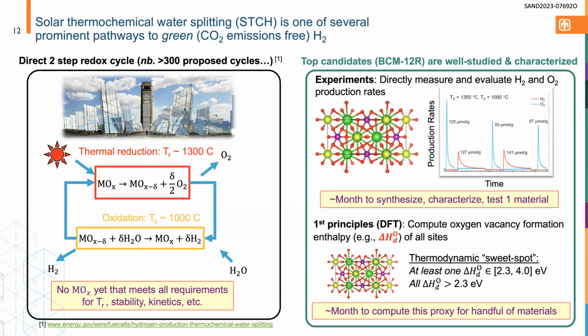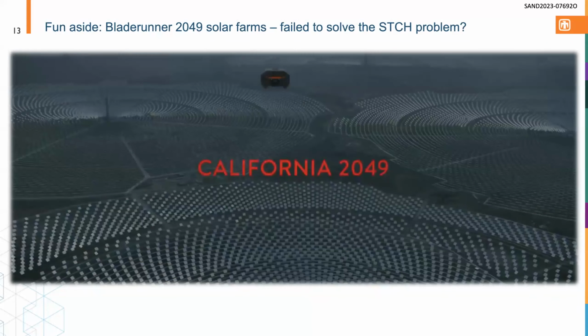So people typically turn to DFT, where they compute the oxygen vacancy formation energy, and we generally know that there's a sweet spot: if that value is outside a range of 2.3 to 4 eV, it's not really worth looking at. Typically, we need at least one vacancy formation energy in that range. We want them all to be above 2.3 eV, because if you have anything lower, it's going to be too hard to reoxidize. And again, it takes months to compute this proxy for STCH performance for a reasonable number of samples with DFT.